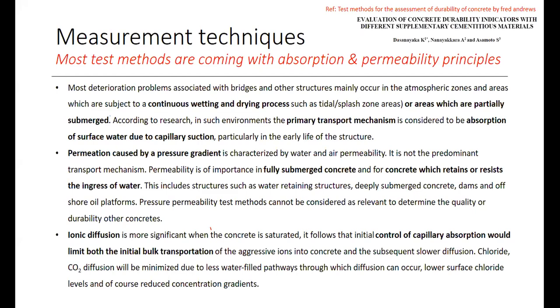So if we want to measure or predict the durability issue for a particular concrete element, the main thing is that we have to measure the ability of absorption, because the main durability issue will come with the primary transport mechanism of absorption. Since it is the primary mechanism, if I want to ensure that my structure will withstand 100 years or the so-called requirement, we have to identify the resistance the particular concrete element delivers against absorption. This is the first phase.